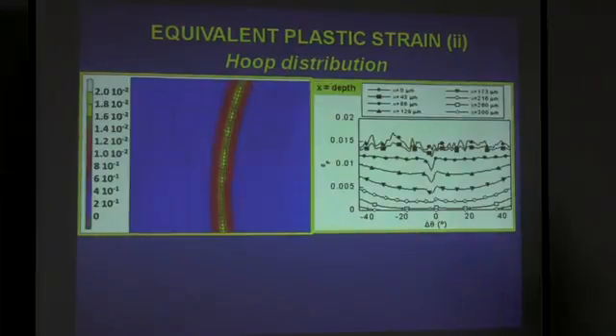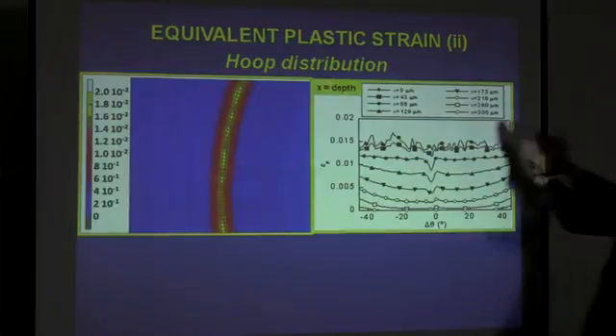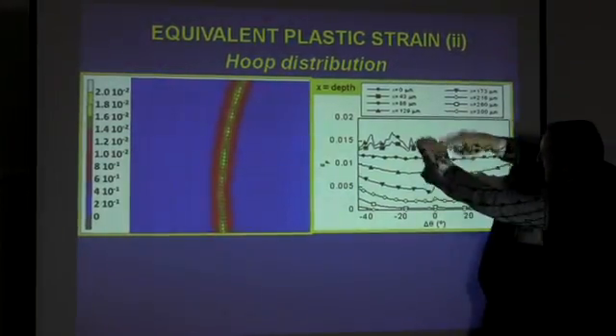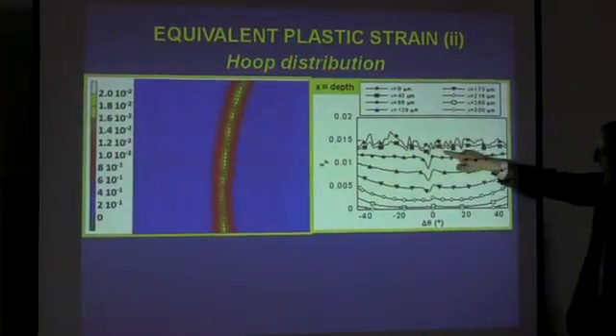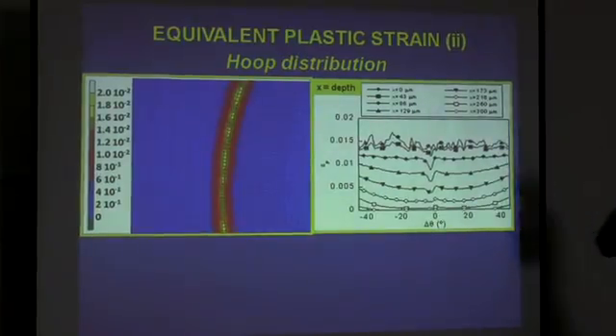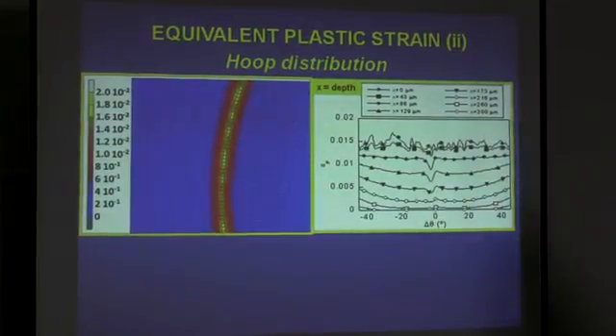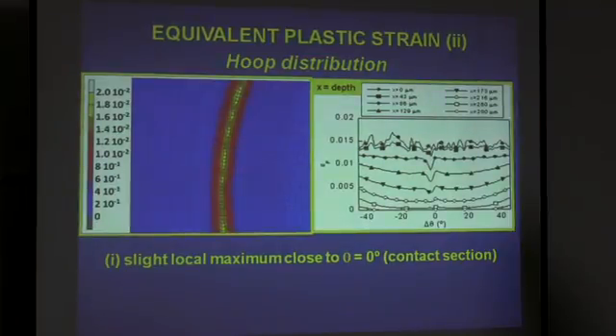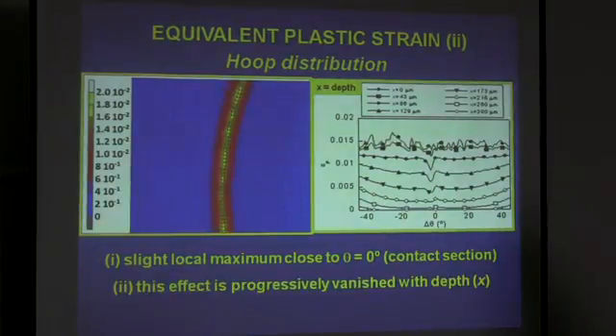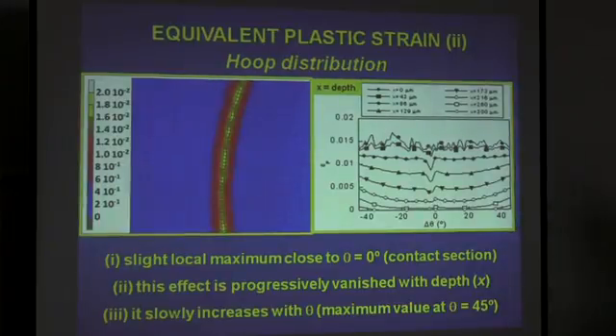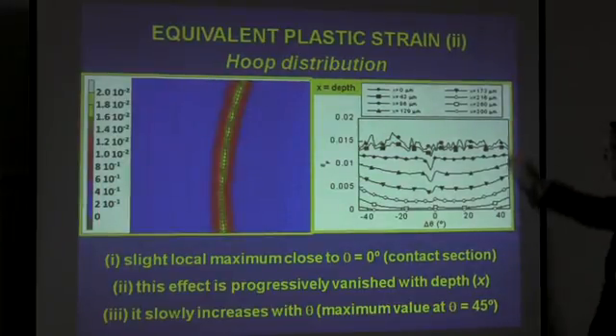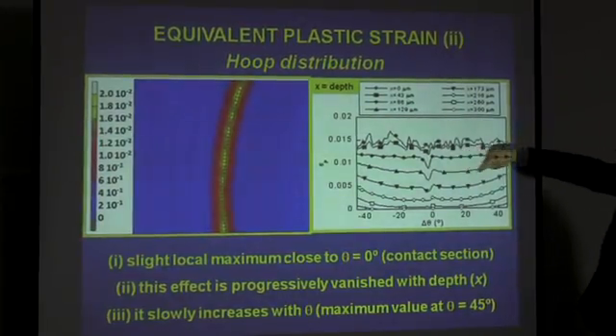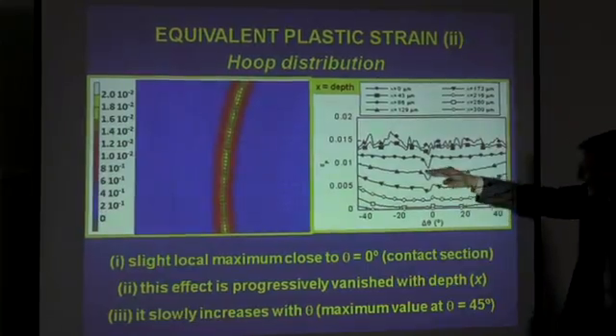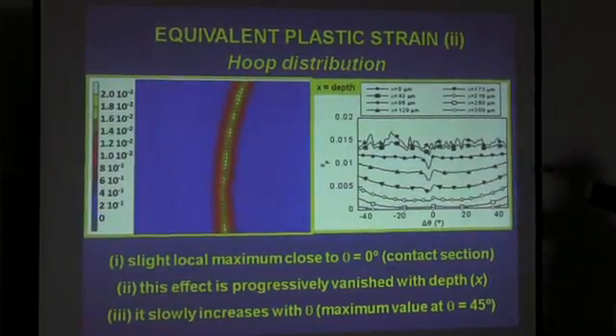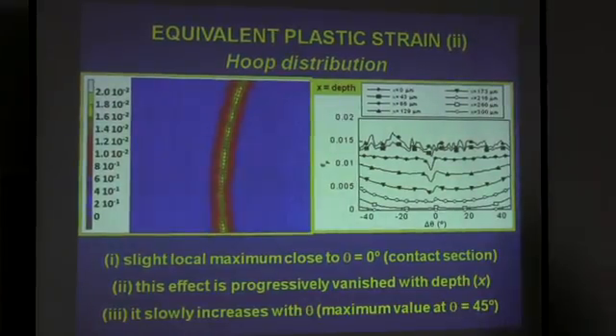And with regard to the hoop distribution, we have this concentration in the contact plane, but we have a minimum. And with a waving distribution, we have higher strains at different angles from the contact plane, because they are cumulative plastic strains. A slight local maximum close to θ0 contact section. This effect progressively vanishes with depth, that's logical, and it slowly increases with θ, with maximum more or less at 45. You see this slight increase. We have a local minimum, a local maximum, and the trend is slightly increasing as we separate from the contact plane, as the angle increases.